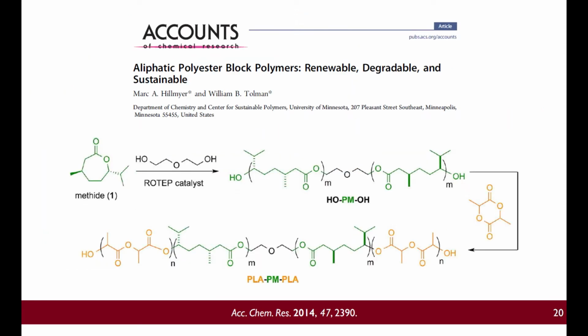Bill Tolman and I spent many a year working on this polymer, which is also a block polymer of orange, green, orange in this case. But now we've put polylactide at the ends, this bio-based thermoplastic PLA. PLA is a high glass transition temperature material, but what we did is we put something called polymenthide in the middle. Now polymenthide has two interesting characteristics.